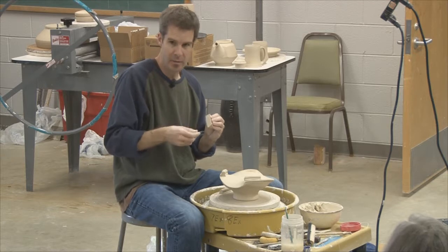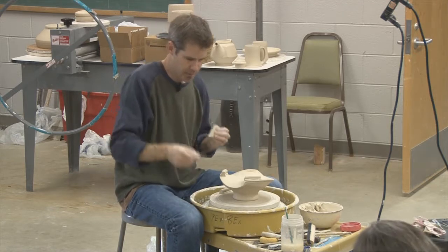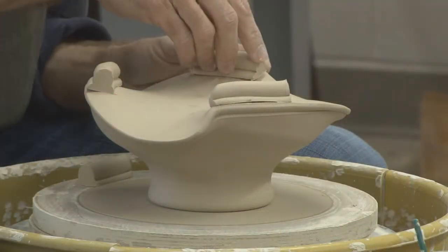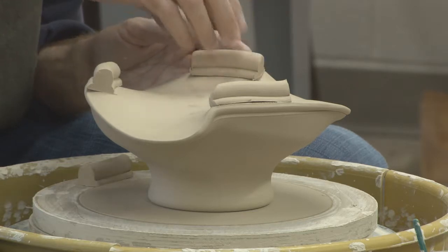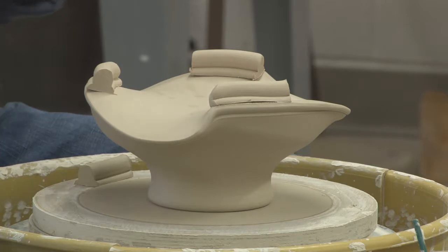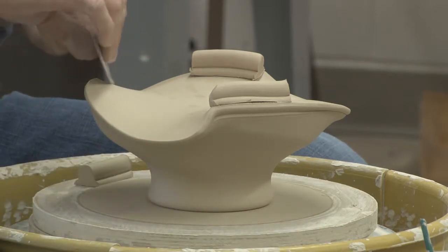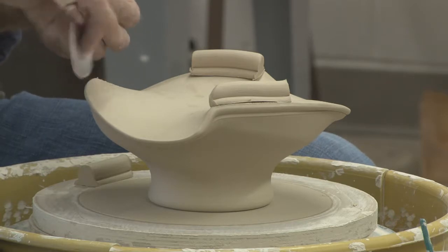Does anybody ever do that? Does anybody know that trick? If you're working with porcelain, sometimes the porcelain can flux a little bit and things can stick together, like lids can stick to the pots. So you put a little bit of alumina hydrate in your wax, and when you wax your pots, when the wax burns away, there's this little fine dusting of alumina hydrate, and that'll allow you to get lids off easier if you have trouble with your lids. And I put that on the feet of my pots so they can slide on the shelf.